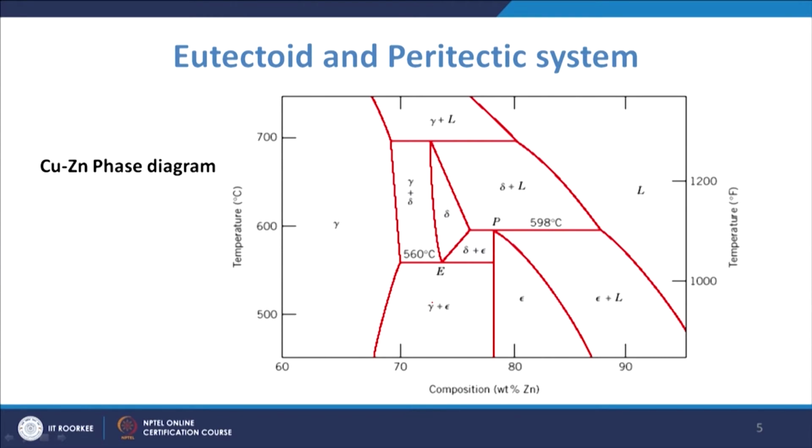such phase diagrams, even for non-ferrous systems, typically you see that a lot of such cases appear where you have reaction products. As you come down you will have different reaction products because the solubility will be different as the temperature is changed. If you talk about other systems, like the copper aluminum system, there also, when you are in a higher temperature zone, the solubility of one phase into the other is more, while when we decrease the temperature the solubility is decreased. So, what happens is that the supersaturated phase will again be likely to precipitate, and this concept is utilized for bringing in hardness, which is known as precipitation hardening.